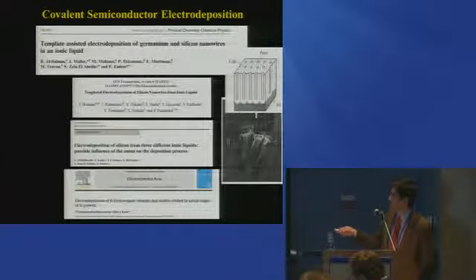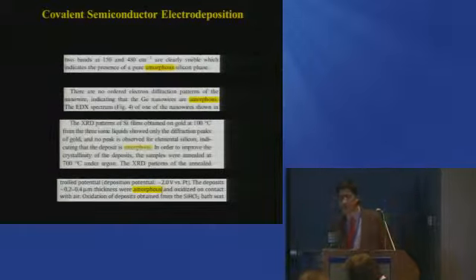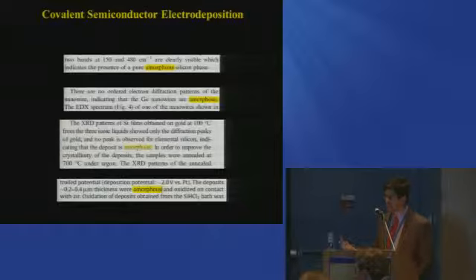However, if you look at the details in this literature, you know that consistently there's a problem, and there's a reason why people don't use this on a routine basis to make silicon or other semiconductors of interest. When you read between the lines in all of these papers, the materials that you get out are all amorphous. They're not crystalline, they're not high purity, and they're not of good electrical grade, which means in the context of either energy applications or if you want to make some electroanalytical device, these materials are worthless. And if you want them to be useful, you're going to have to do some sort of refining or some other sort of step, at which point you have to ask yourself, why am I doing this electrodeposition to begin with?